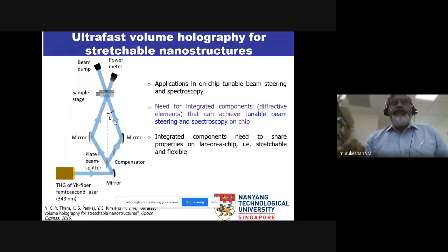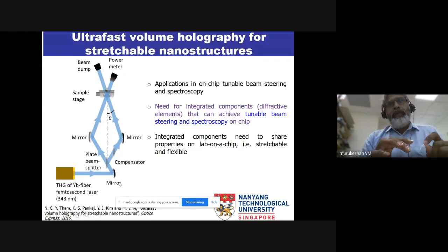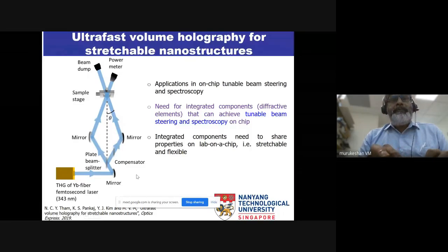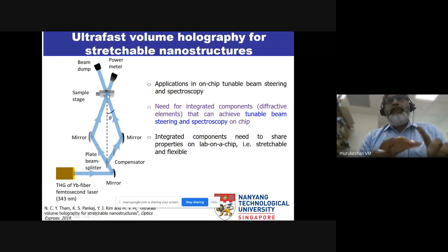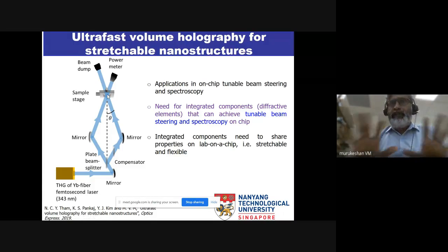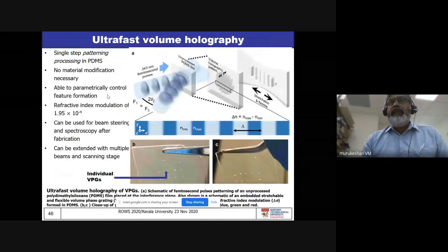So what we need to do is that we need to first identify the optimum wavelength, and we have to have the configuration. And I'm going to show you a configuration that is using a femtosecond laser at 343 nanometers. And we were using this configuration to do this patterning. The normal interference patterning, not near field, okay? The normal interference patterning. And you can see that these are 2 femtosecond pulses.